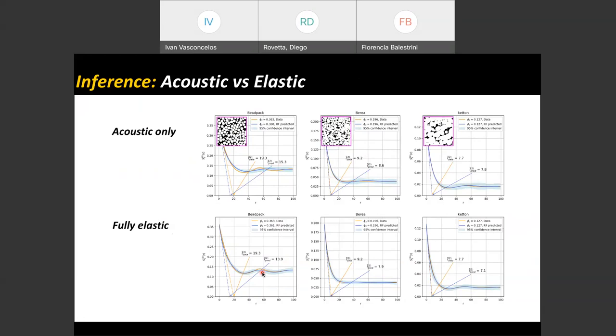The reason for this physically is that the wavelength of P waves and shear waves are different. So the dependence in geometry as a function of frequency complement each other from these two wave modes in resolving the structure of these more complicated two-point correlation functions. Now, this result that you see here is very promising. Okay? This result says that if we can measure wave speed and attenuation as a function of frequency, we may stand a chance of not only resolving contrast or volume fraction, but also the geometry of the material. This has long been a holy grail for this field. And now we think that we are much closer to getting this.